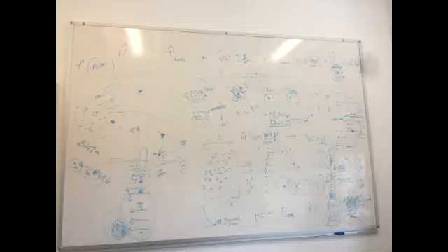You expand it into a sum of some basis functions. And these basis functions can be plane waves, so that would be explicitly Fourier transform. So this method is called plane waves basis. Or this phi can be a sum of real atomic orbitals. And still you want maybe to try to modify these orbitals a little bit, compress them, extend them, so that they create a more complete basis, so that it's a sufficient basis to describe your function.